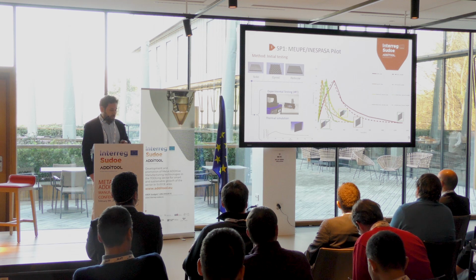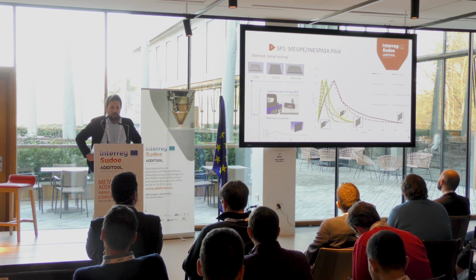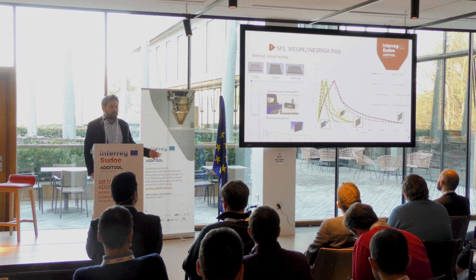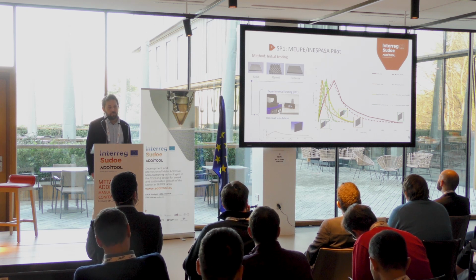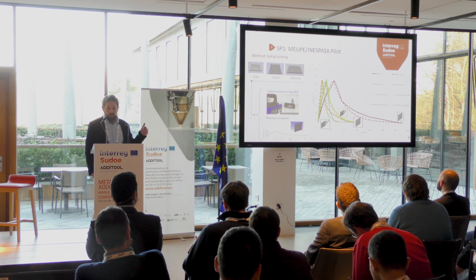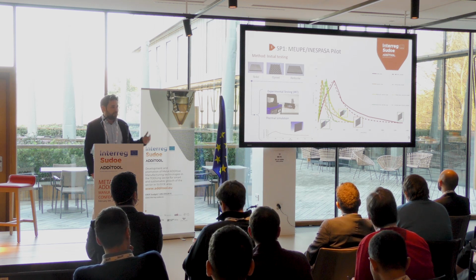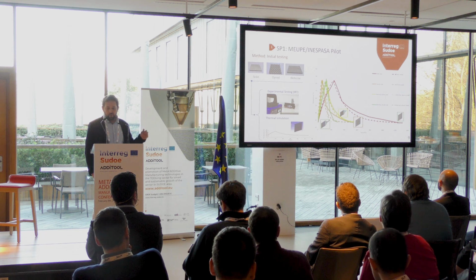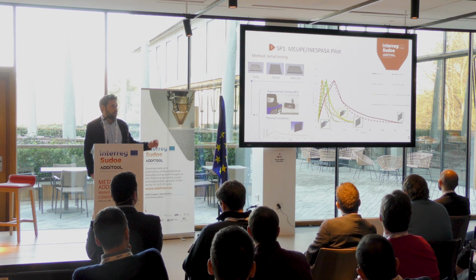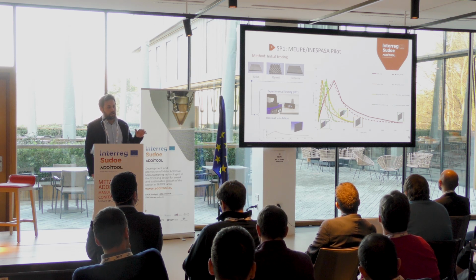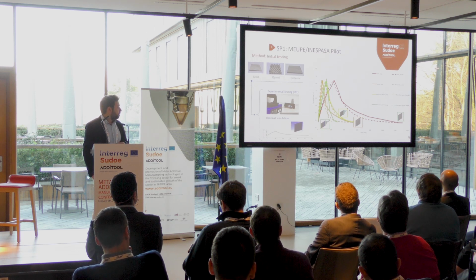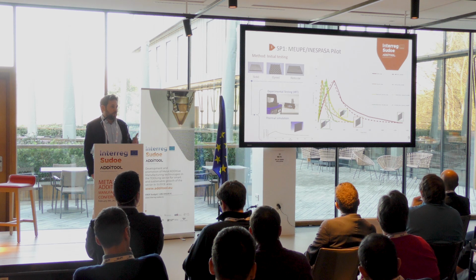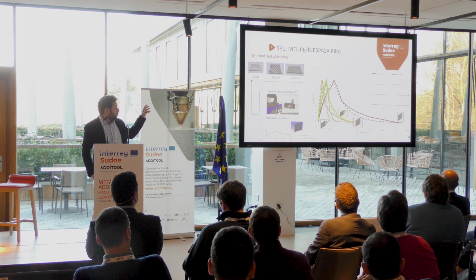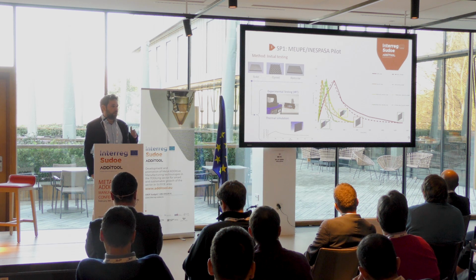So once the material is chosen, we manufactured some coupons to validate the design proposal. You can see there a gyroid, which works like fins, and what we call a reticular structure that has internal cavities, so we can induce air inside that coupon. We perform some testing, heating it, and also manufacture a solid sample so we can compare with a nominal material.